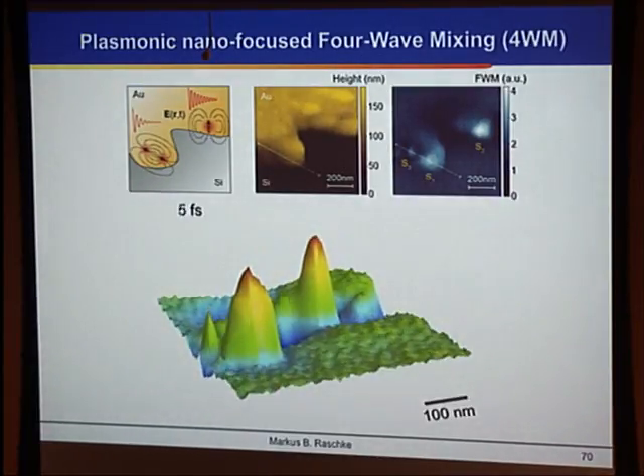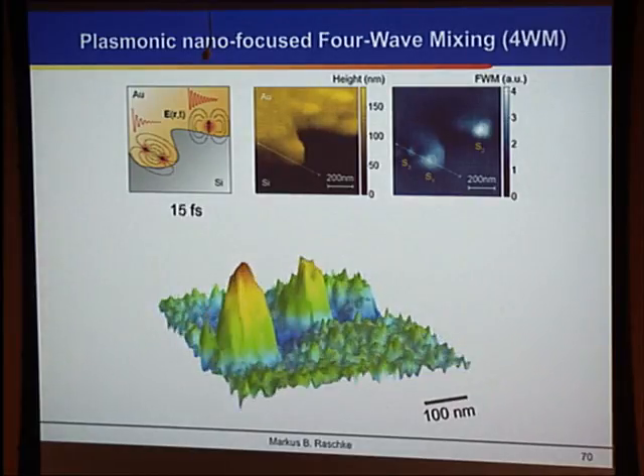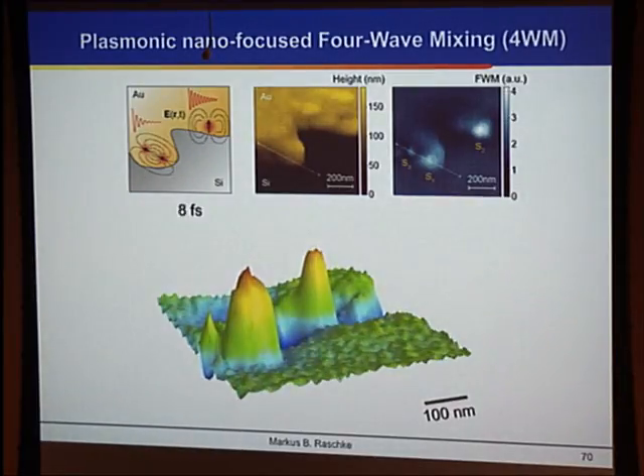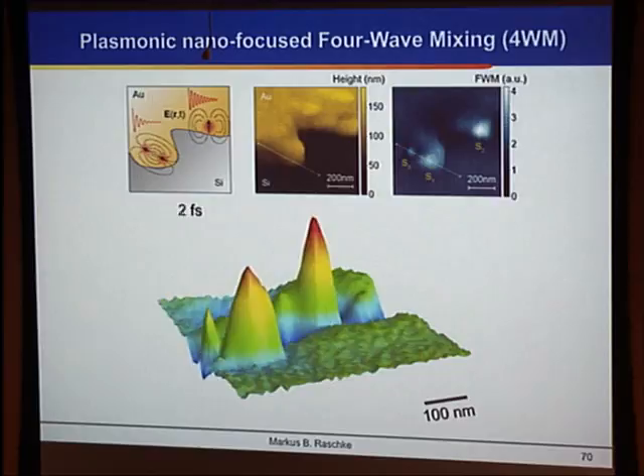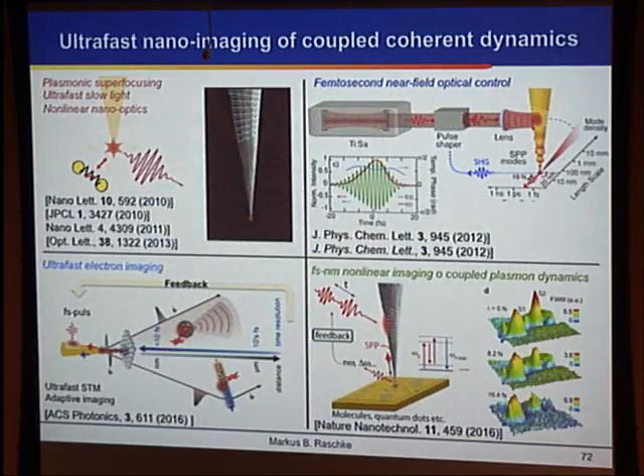It's a short sequence, admittedly, over a very small length scale, but with the highest time resolution. So we can extend this tool in many ways to different capacities. We use the second harmonic response of the apex for a pulse shaper, by which we generate these pulse replicas.